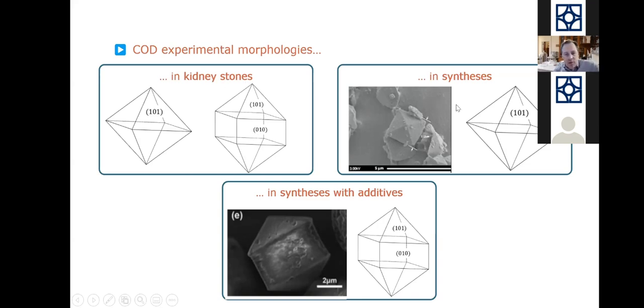In synthesis, we can't introduce this, but we have seen that by adding additives, typically complexing agents, of which there are many, we grow a surface in this area, showing that we have here a 010 surface appearing. So you see here this enlarged octahedral structure.